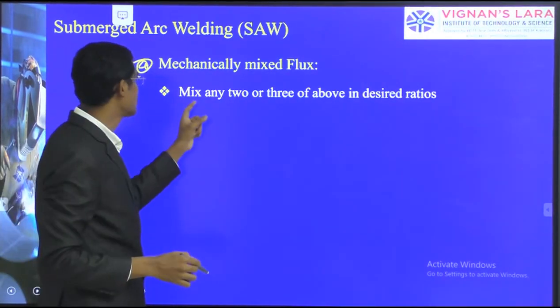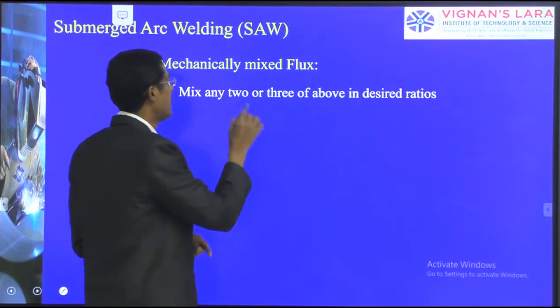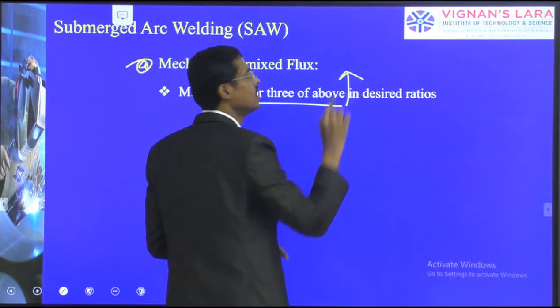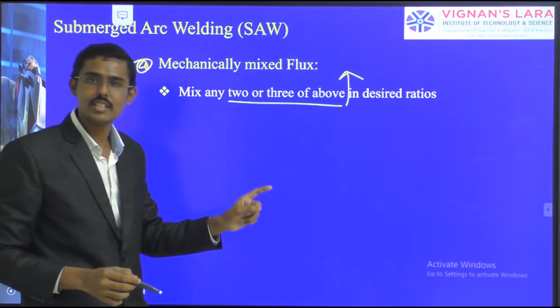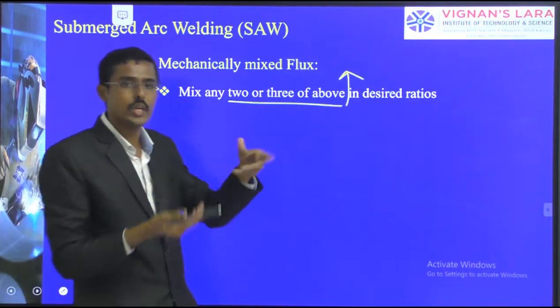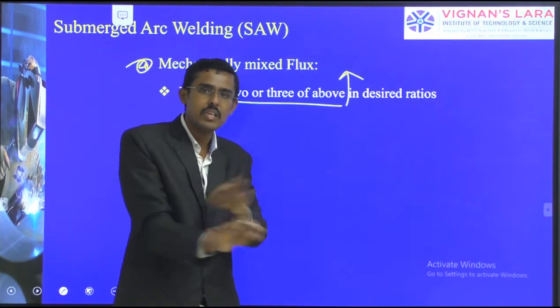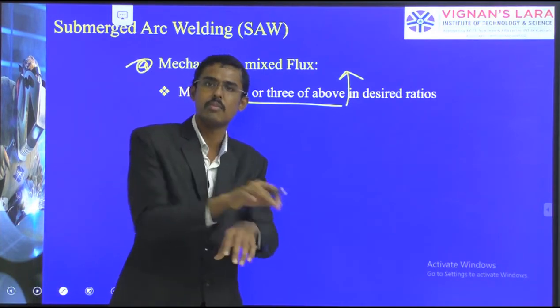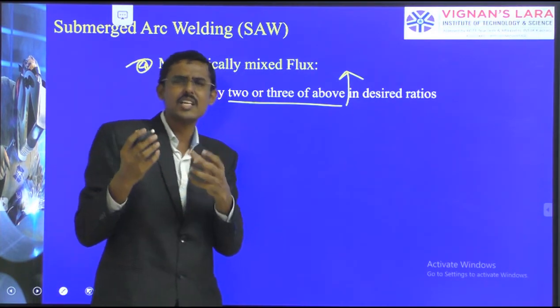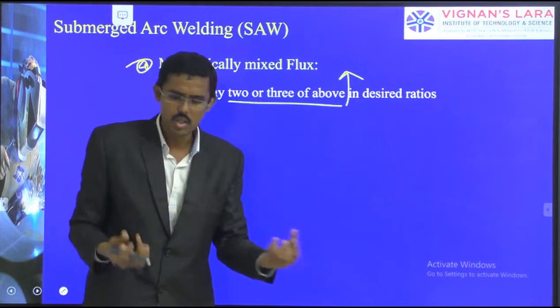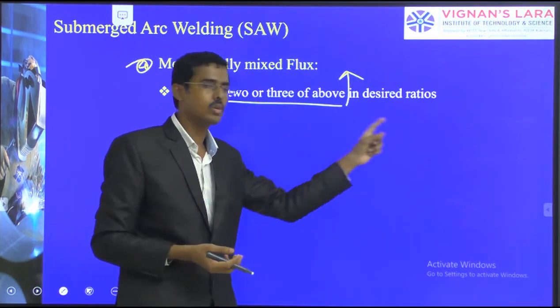Then the mechanically mixed flux. Here we mix any two or three of the above. What have we seen above? Fused fluxes, bonded fluxes, agglomerated fluxes. We take any two of these and mechanically mix them in a desired ratio, such as 2:1 or 3:2. Likewise we can mix.